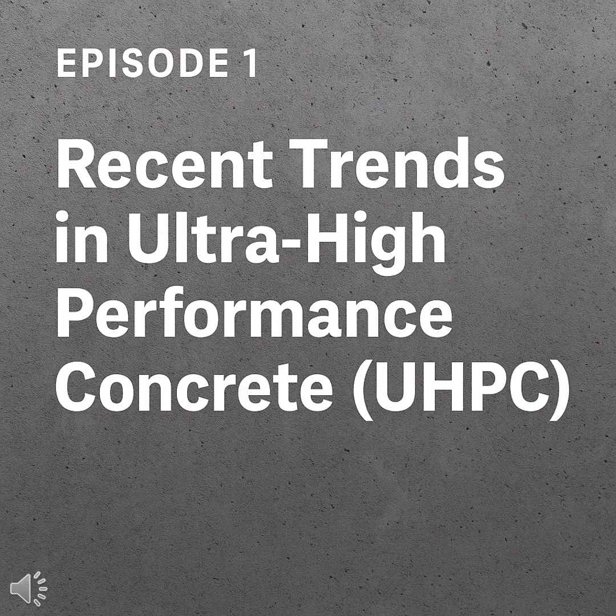Okay, let's talk properties then. What kind of numbers make it stand out so much? Strength is probably the headline. Compressive strength, often over 200 MPa. 200. Wow. And normal concrete is? Typical stuff for buildings, bridges, maybe 20 to 42 MPa. So yeah, UHPC can be anywhere from 3 to like 16 times stronger in compression. That's a huge leap. And its tensile strength, its ability to resist being pulled apart, is also way better, often above 20 MPa. Normal concrete is famously weak in tension.